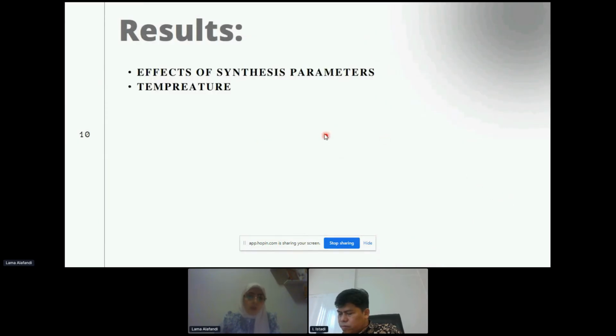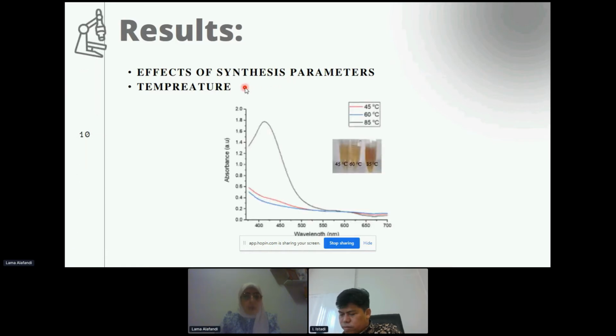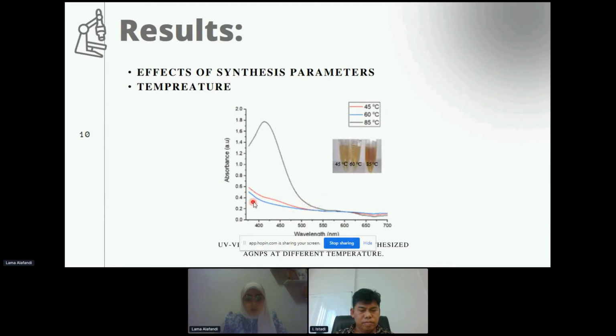Moving to the other part of the results, which is the effect of synthesis parameters, first we start with temperature. Those results were obtained using UV-Vis. First, to start this experiment, we started with 45 Celsius incubation temperature for only 10 minutes of reaction time. We can see that when we used 45 Celsius and 60 Celsius incubation temperature, there was no formation of silver nanoparticles. Again, it was done only for 10 minutes, the reaction time. Then when the temperature is increased to 85 Celsius, during 10 minutes, we see formation of silver nanoparticles. So we can conclude that increasing the temperature increased the formation of silver nanoparticles.